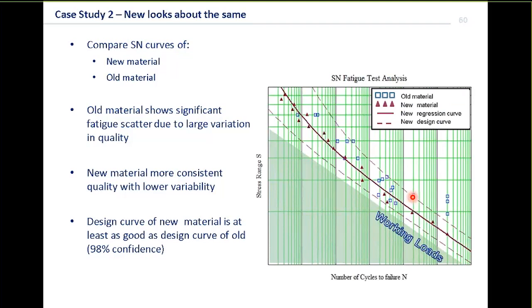So now, with the same sort of confidence, we can see that even though the regression curve was below, in terms of its design curve, it's above. And that's because it's a more consistent quality of material than the old one. So in this case, with a 98% confidence interval, we can actually say that the new material is at least as good as the old one, even though the regression curves don't match.